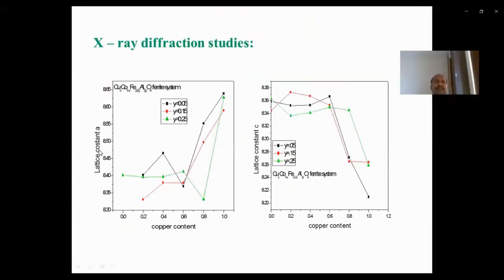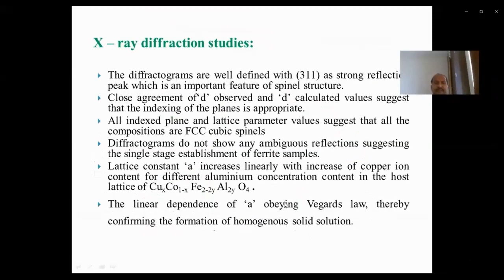With the help of X-ray, we observe that lattice constant a increases with increasing copper content, and lattice constant c decreases with increasing copper content. We observe a well-defined strong 311 reflection peak, which is an important feature of the spinel structure. Close agreement of the observed and calculated d values suggests indexing of the planes, and the lattice parameters suggest that all the compositions are FCC cubic spinel. The diffractogram does not show any extra reflection, suggesting single phase formation of the ferrite samples.